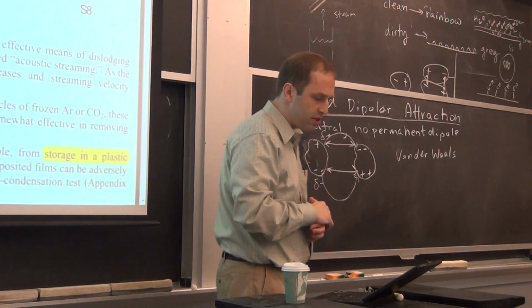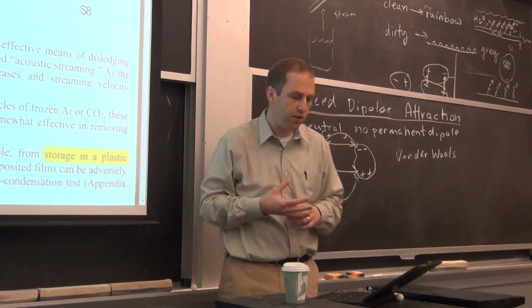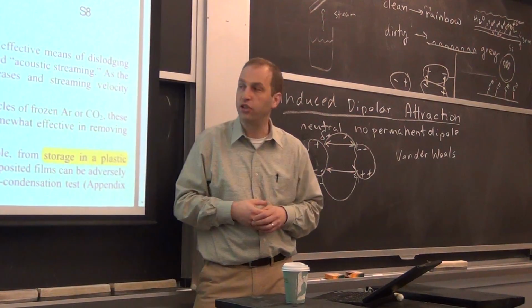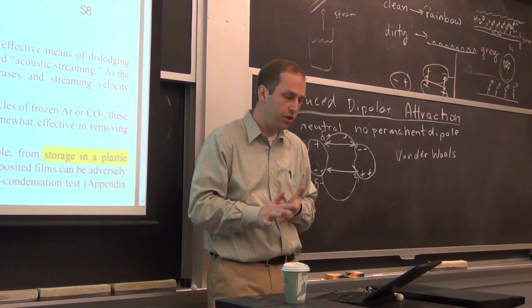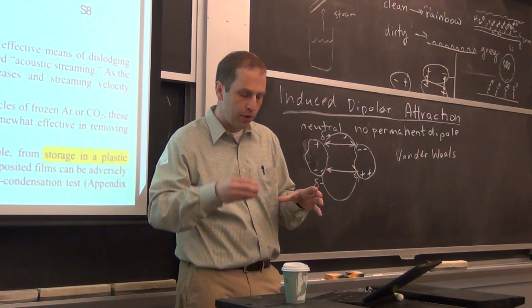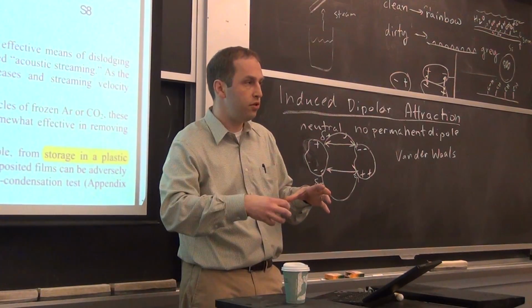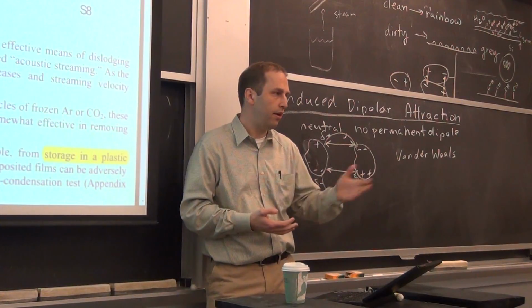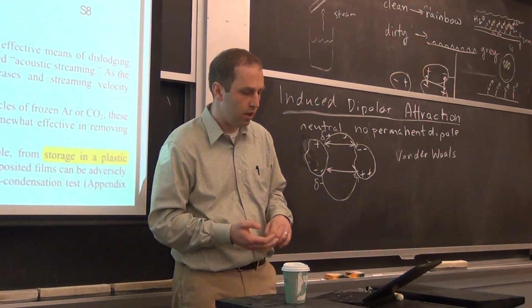Particulates are a big concern I mentioned before. Small particulates are very hard to remove, so typically they're removed by what's called megasonic agitation, which is megahertz scale agitation. It's very simple to do this. You can just take the wafer and put in a transducer in water that emits megasonic waves, and then shine it on the wafer, and it'll clean the wafer.